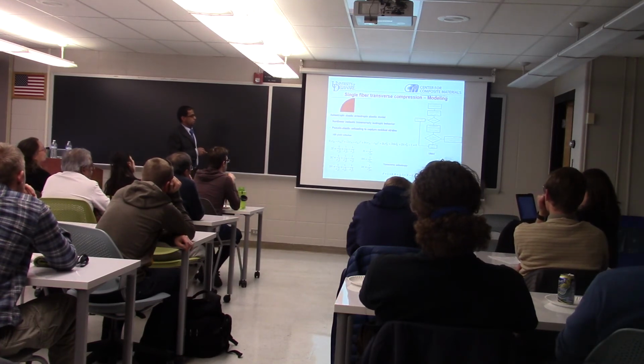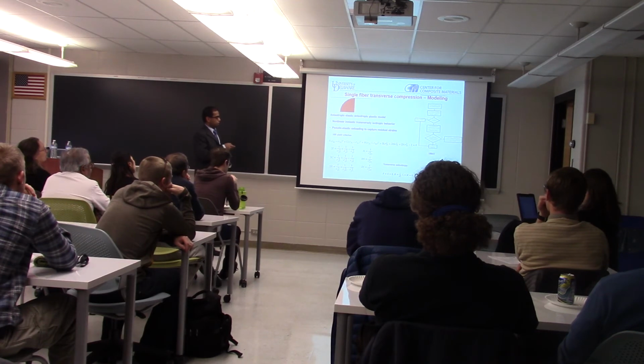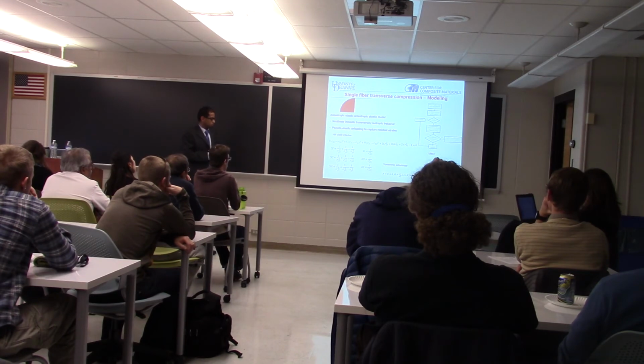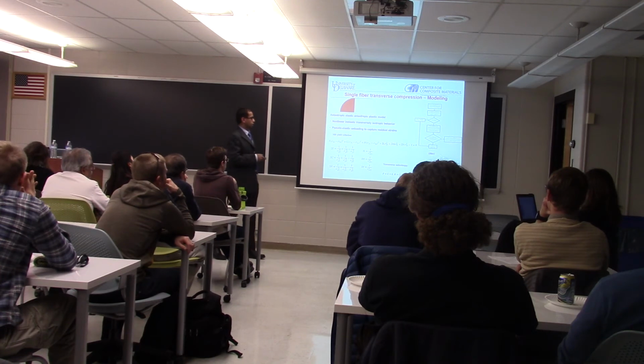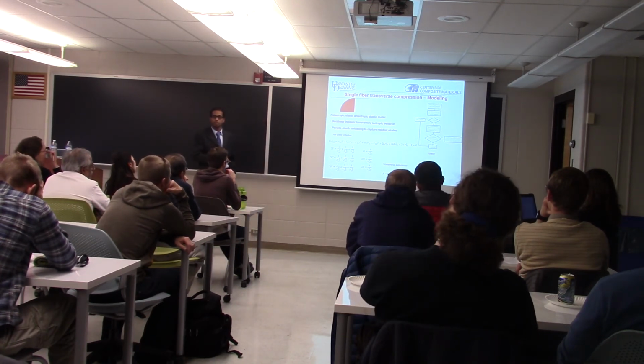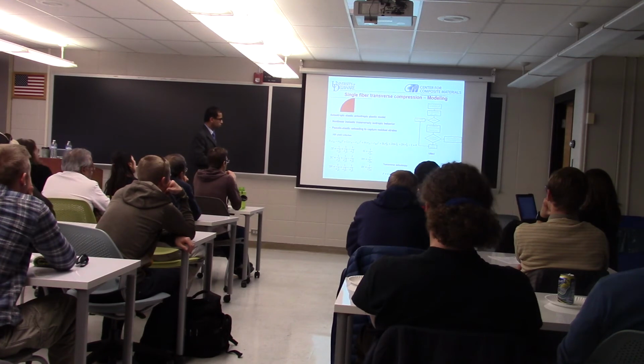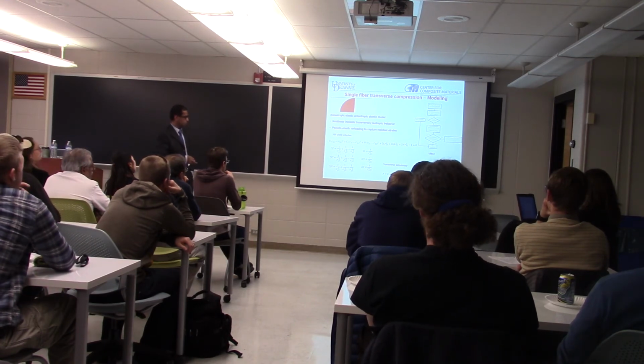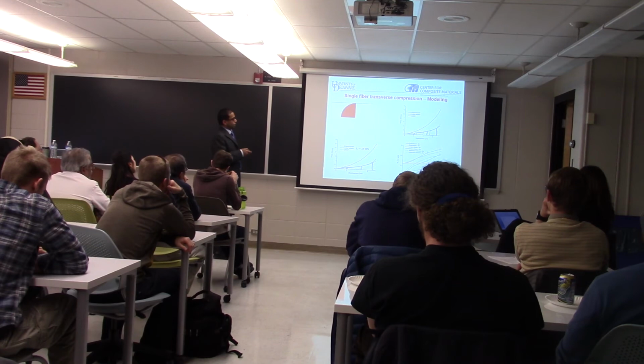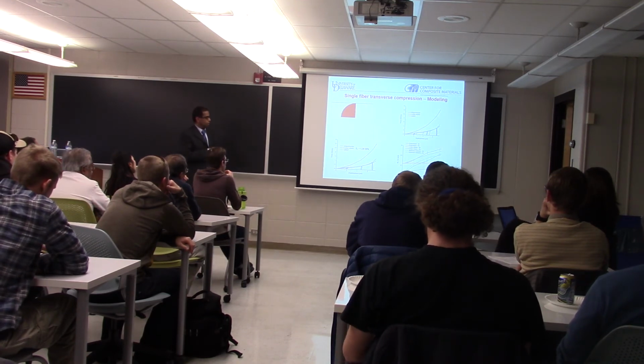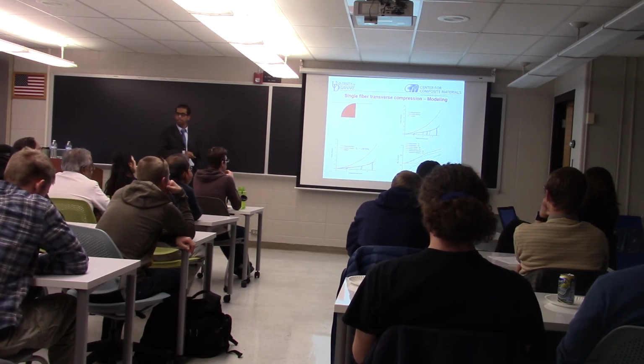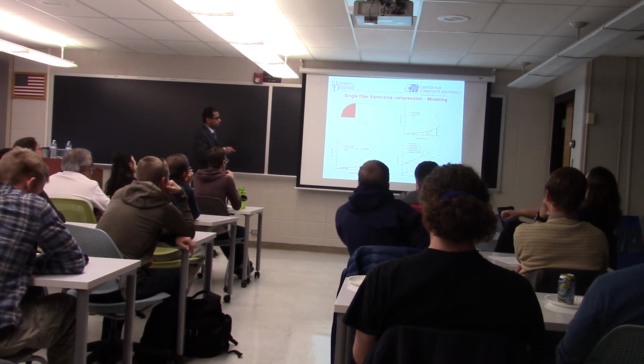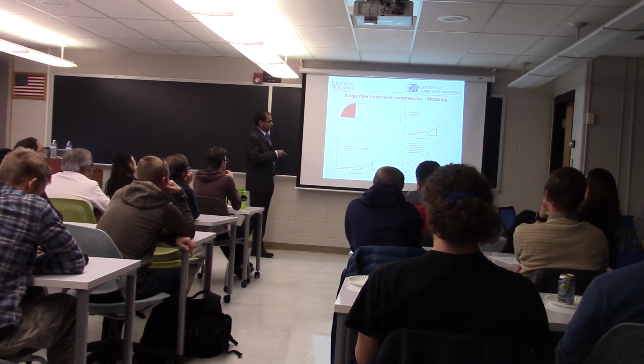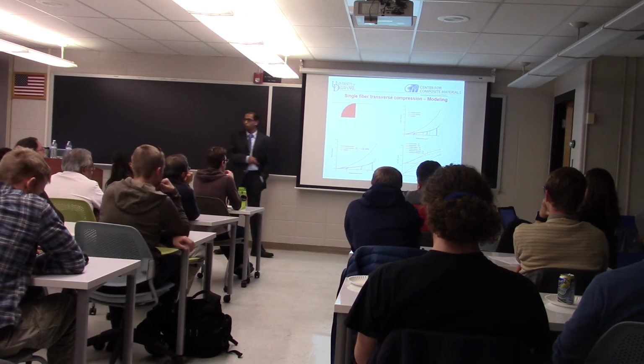So now the next step is, with this experimental observation, we wanted to model this experimental behavior, where we implemented a user-defined material model in LS-DYNA. Here we used a plasticity approach, that is Hill's yield criterion, to model this transversely isotropic inelastic behavior. I won't go too much into the details. The nonlinear inelastic model shows much better correlation to the experimental results compared to a linear elastic assumption. And the model is also able to capture the energy absorption associated with unloading.